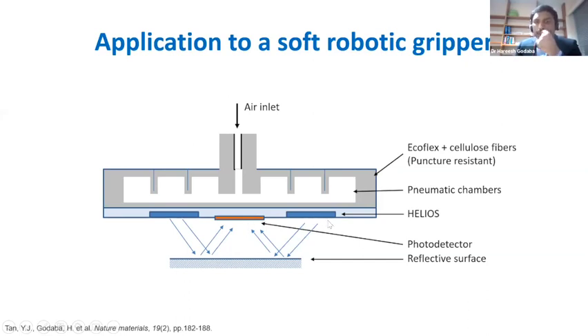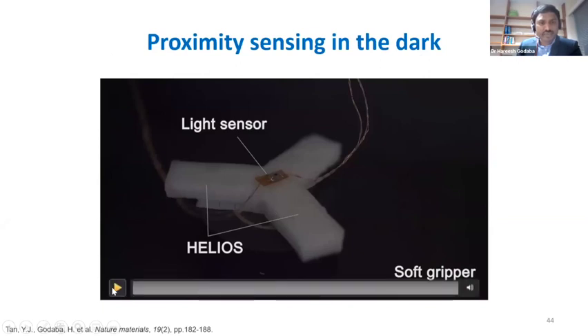And then since we wanted to make use of this self-healing capability to basically make this gripper more resilient, what we did is we also made this gripper from material that is puncture resistant. So if we take a normal silicone material like Ecoflex, and then we add cellulose fibers, so it generates a matrix that basically can make this materials puncture resistant. So then taking these two together, we develop this type of gripper.